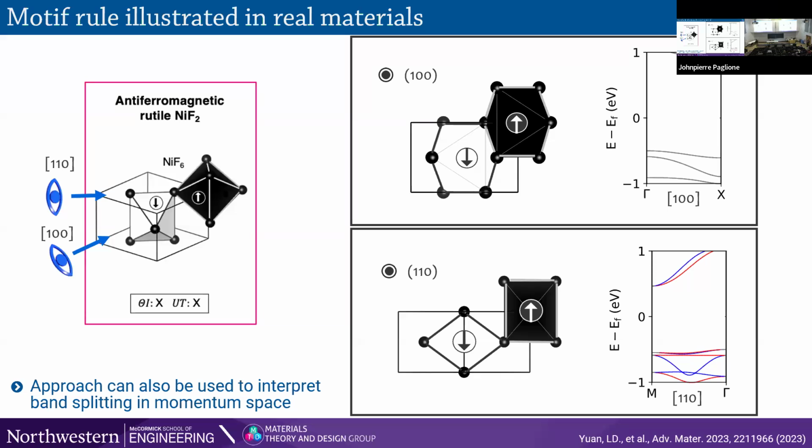Yeah. So the question I think was, in the presentation I gave, I was making substitutions like a chemist would, and I think that's fair. That's actually a large part of what my group does, is to identify known structure types and look for new compositions in known structure types. The question pertains to the discovery of really new structure types, which I think is incredibly difficult for binary compounds, still difficult for ternaries, but the phase space that's open is quaternary compounds. But then we have Pauling's rule of parsimony, which tells us it's probably going to adopt a simpler structure or be two-phase. So there are generative algorithms, both physics-based, where you can do mutations and cut crystals together and assemble them, which will allow you to sample new structure spaces, as well as